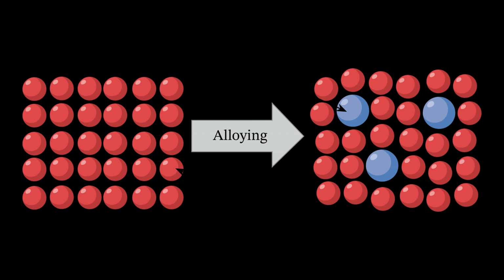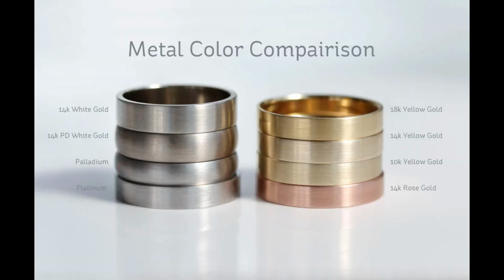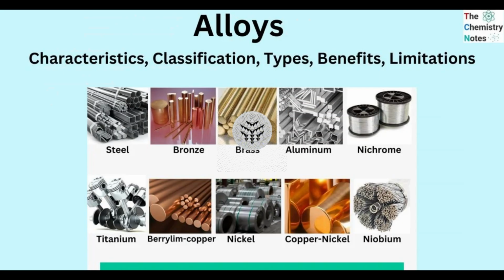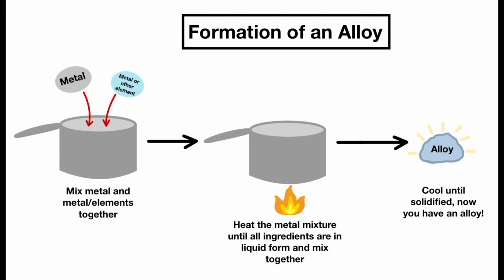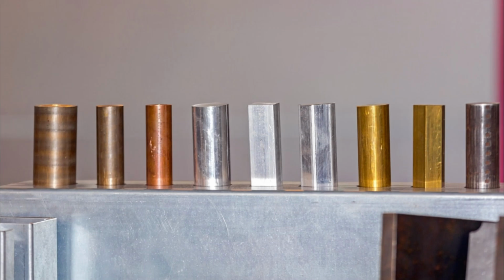Contrary to the norm, the RHEA defies expectations by maintaining its integrity even at frigid temperatures as low as liquid nitrogen, minus 196 degrees C. While most elements and their alloys become brittle at low temperatures, some even up to 800 degrees C, this RHEA remains resilient.